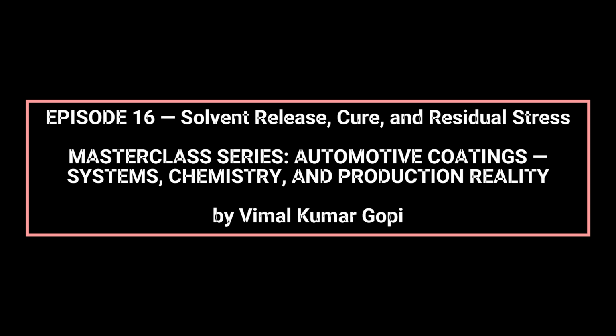The interplay between solvent release and cure generates residual stresses within the coating. Residual stress arises from constrained shrinkage, thermal gradients during bake, and differential cure across film thickness. High residual stress manifests as microcracking, adhesion loss, or premature gloss reduction, while low residual stress can compromise mechanical integrity, such as stone chip resistance.